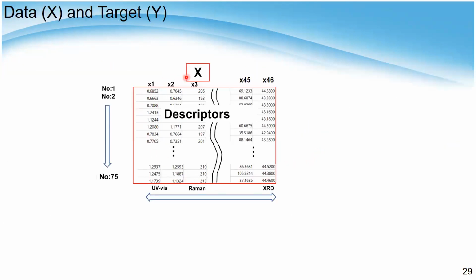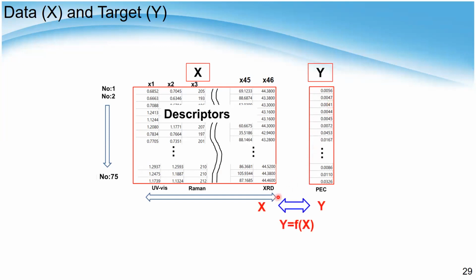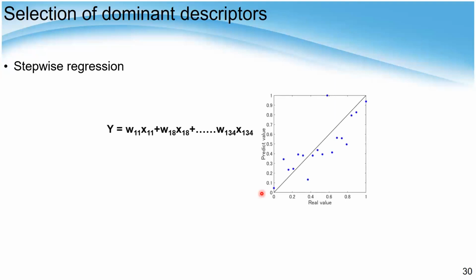So in this case we collected 46 features from the analytical data for a sample set of 75, and the Y values are the photocurrent value at 1.23 volt. These X and Y are correlated with machine learning as Y equals F of X. And of course, not all the X values are equally important, and actually many of them are not useful for prediction of the performance. We can select the important descriptors using various methods in data science. Here's one of them, called stepwise regression.